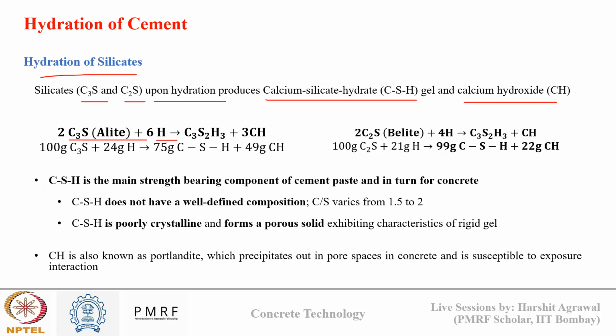C3S reacts with water to form CSH and CH. 2 moles of C3S combine with 6 moles of water to form 1 mole of CSH and 3 moles of CH. In terms of quantity, 100 grams of C3S requires 24 grams of water to produce 75 grams of CSH and 49 grams of CH. Whereas for belite C2S, 2 moles of C2S react with 4 moles of water to form CSH and CH. So 100 grams of C2S will require 21 grams of water to produce 99 grams of CSH and 22 grams of CH. So we can see there are two hydration products forming, CSH and CH.